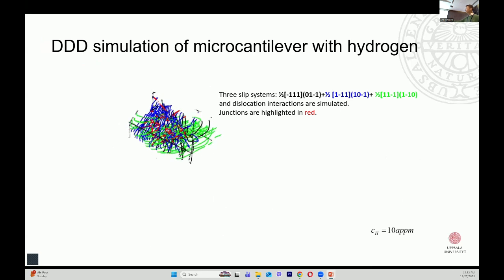So if we consider a finite volume and couple the dislocation dynamics simulation to finite elements approach, we will be able to simulate the operation of the dislocations in the volume so that we can capture the microscale plasticity in a real microscale experiment. And further, we can introduce hydrogen into the dislocation dynamics framework. And we do this by considering the hydrogen modified velocity of dislocations as well as the hydrogen lowered dislocation energy profile. If the energy is reduced, the line tension of the dislocation will be reduced, and dislocations will be easier to generate. So this is the general idea.